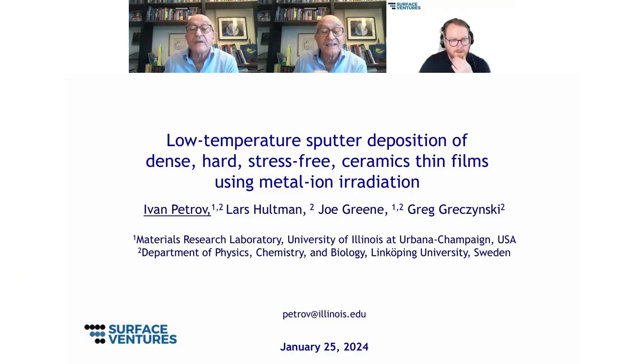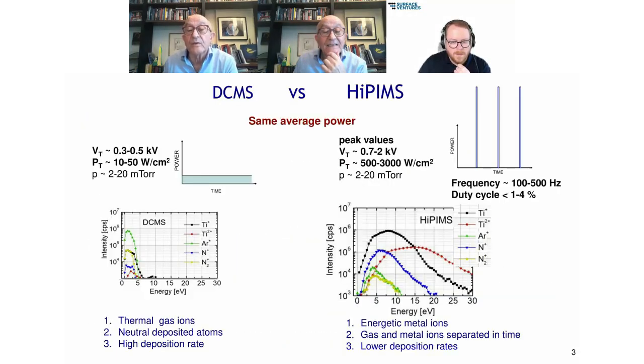In HiPIMS, with the same average power, we pulse. The frequencies are in the hundreds of hertz, and the duty cycle is a few percent. That gives us peak powers 2 to 3 orders of magnitude higher.